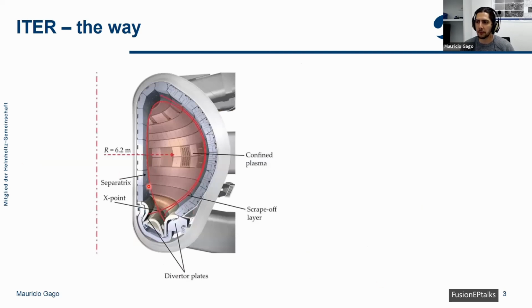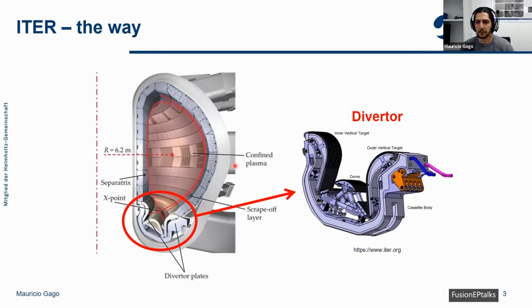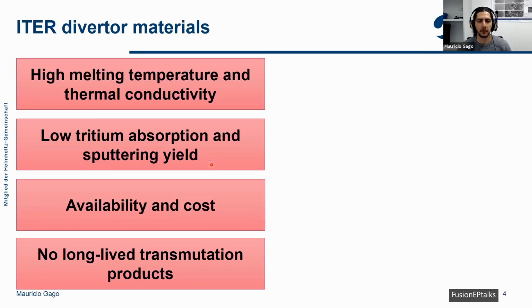Inside the reactor, we will have the plasma being contained, which will be at around 150 million degrees C. And in order to regulate these hot particles inside the reactor, the magnetic field will be configured such that excess particles and heat can be extracted by causing them to hit the zone here, which is known as the divertor. This will cause the divertor to be the area where the plasma-facing materials are exposed to the highest loads inside ITER and inside most reactors, in fact. Because of this, we will have very high loads.